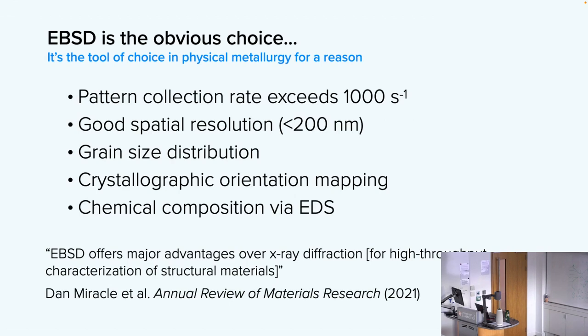So if you want to do this, the easiest and the most obvious choice is EBSD, right? Which has been sort of the tool of choice in physical metallurgy for 20 years or so. You can do it reasonably fast. These days, you can acquire EBSD patterns at a rate of about 1,000 per second or so. You get pretty good spatial resolution. You, of course, can directly measure the grain size distribution and the crystallographic texture. And then as a bonus, because you've already put it in a microscope, you can do chemical composition by EDS. So this is really obvious. And a good friend, Dan Miracle, made this statement in his review article on high-throughput characterization of structural metals back about 4 or 5 years ago. Naturally, we decided not to do it that way.